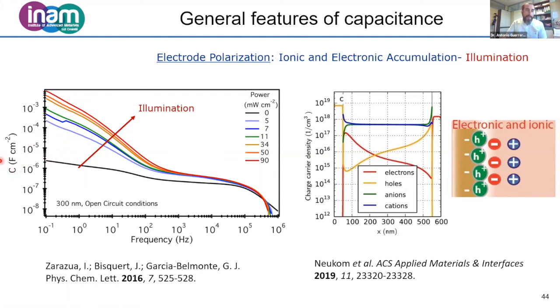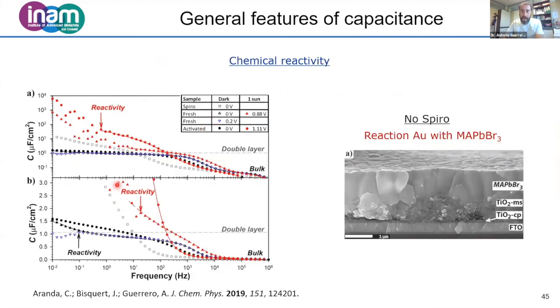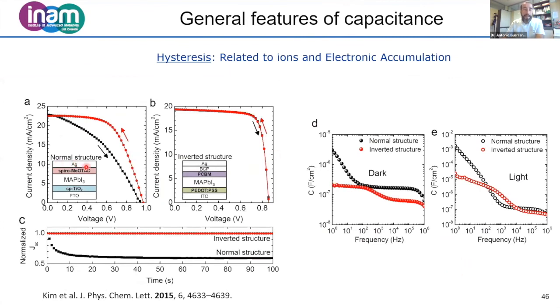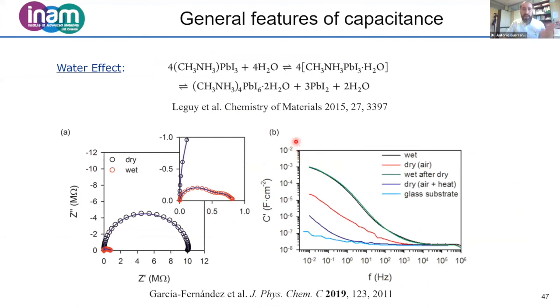And this is why we see that the interfaces are being charged. And to finish with the contacts, we observe the signature of the reactivity. For example, in this device, we use methylammonium lead bromide cells without the spiro, so we promote the reaction of iodine with gold. And in this case, we start observing loads of noise in the low frequency region, and we attribute this to the chemical reactivity. We have done similar experiments with silver, and we also observe the signature of noise. The results from impedance are very important because how the interfaces are being charged is totally connected to the hysteresis phenomena. Okay. And I'll give you one more example and then I can stop here.